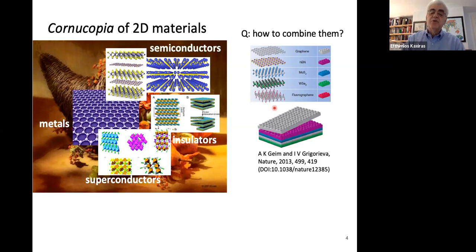And what I'm going to argue is that the stacking of these materials doesn't look anything like Legos, because Legos are very nicely structured to fit exactly one on top of each other. These materials do not fit well with each other. And even if they're slightly misaligned, the layers of the same material don't quite fit very well. And this creates all sorts of really interesting possibilities and in fact enriches the physics, makes it even more exciting.